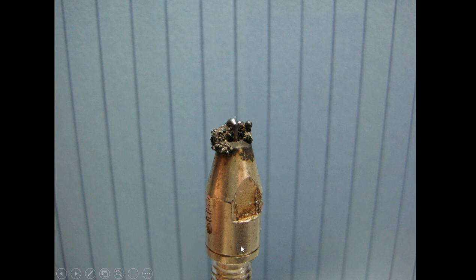Now this is a chrome zirc tip. It's a special type of a hardened tip. And we know this because it has a band around it. All chrome zirc tips have a band around them. So this one was picking up so much heat and was getting so hot from the plasma, and failure came as a result of course, the spatter ball sticking to this cluster that's building on the side of it. This is an overheated condition that should be addressed through technique, parameters, whatever, or maybe clearly just a bigger, better contact tip.